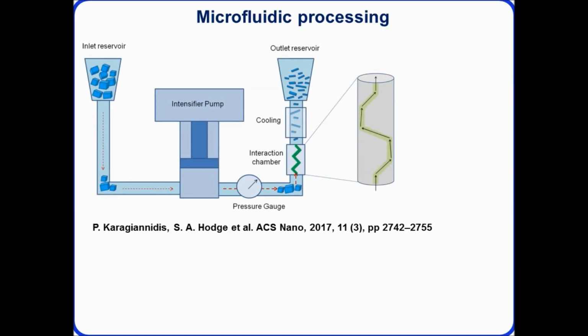Essentially, this schematic shows the process. So we have an inlet reservoir, and we pump graphite in water with some surfactant through the interaction chamber here, where the high shear forces are generated at the side walls of the chamber. So we are using a Z-type chamber. The graphene exfoliates inside, and then we pass it through a cooling section, and from the outlet reservoir we then recycle the material back through the inlet reservoir.